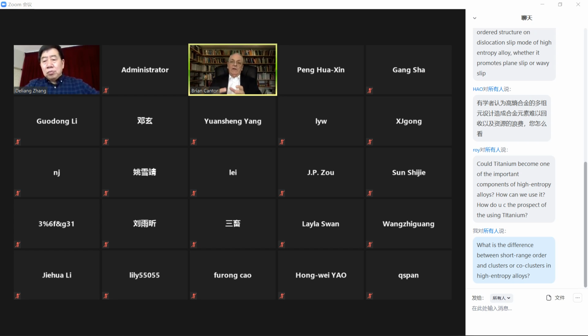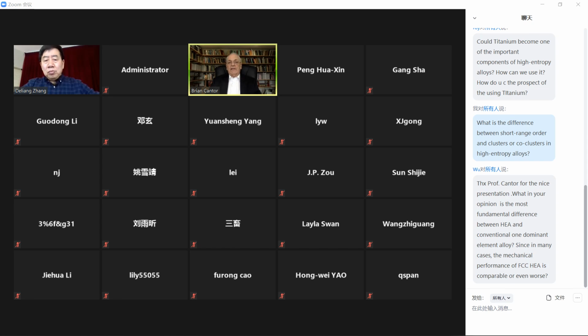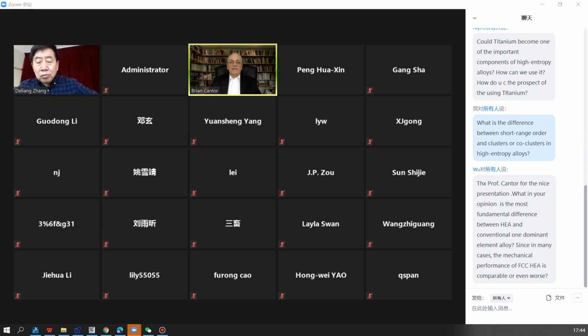Now, the question is, you can start to see short-range order. Does it promote the planar slip or the wavy slip? I don't know that much detailed work has been done on it, but I think we would expect that with the short-range order, it would promote more wavy slip. It would depend a little bit, though, on the stacking fault energy, because if you've got separated partials, and the stacking fault energy stays reasonable, then it's harder to have wavy slip, because once you have partials, they're more fixed in the same plane, and that's what creates planar slip. So it depends. I don't think we know the answer. There's a lot to be studied.